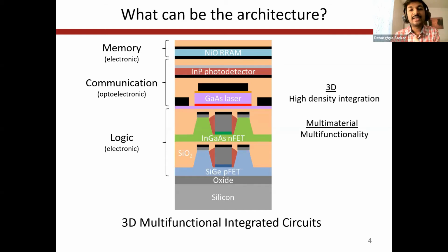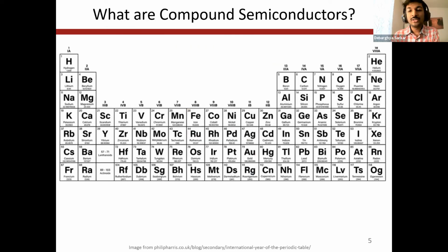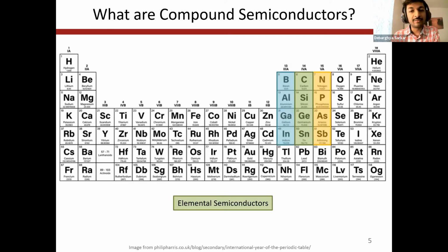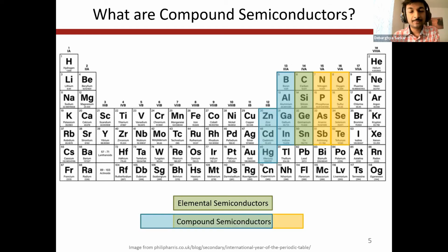Now, when I say multiple materials, I necessarily include compound semiconductors. So what are compound semiconductors? Well, similar to elemental semiconductors like silicon, germanium, etc., which are in group 4 of the periodic table, if you take elements from group 3 and group 5, such as indium and phosphorus, gallium and nitrogen, aluminum and arsenic, and so on, or you take elements from group 2 and group 6, then you form what are called compound semiconductors. And the compound semiconductors typically have much better intrinsic material properties than those of elemental semiconductors. And so they are strong contenders to be used as materials of choice for future 3D integrated circuits.